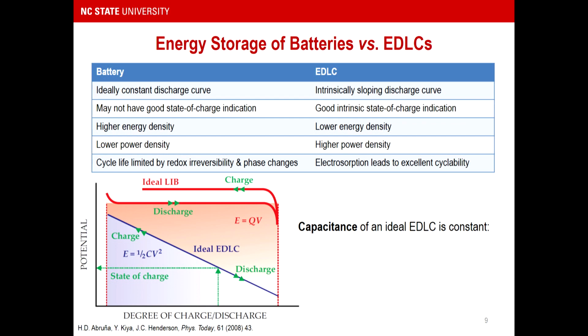For a double-layer capacitor, ideally you have this linear potential versus degree of charge-discharge plot. And if we assume that we could match the capacity of a battery electrode, which would be very difficult, but let's assume we can do that, it shows that even then, at most, the energy stored by this type of device would be half of what you could get with a battery. And that's because of this continuous linear potential dependence on the state of charge, which makes this area of a triangle, which we summarize as E is equal to 1/2 CV squared. The inverse slope of this line becomes the capacitance. And that's really what fundamentally drives the differences between the energy of these devices.